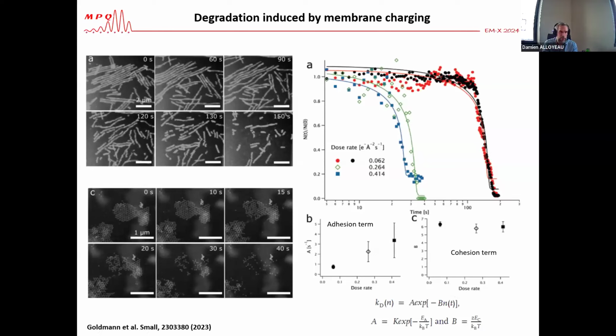And it is well known that when you irradiate the membrane, you change the charge of this membrane, and by an electrification process, you can reach a state where your nanoparticles have the same charge as the membrane, which favors their expulsion. So this kinetic study proves that the structural properties of those nanocrystals are affected by membrane charging and the affinity of the nanoparticles for the membrane.